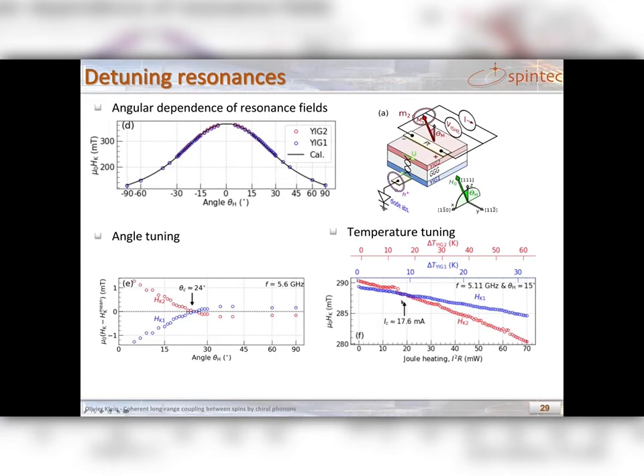On the other hand, when you put a DC current in the top platinum, the top layer, which is close to the source, has a temperature rise about twice bigger than that of the bottom layer, and the current at which the two systems cross is about 18 milliamp.